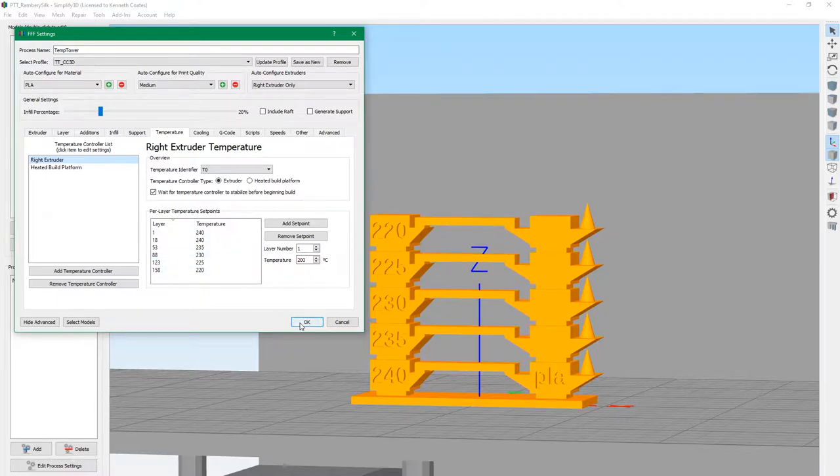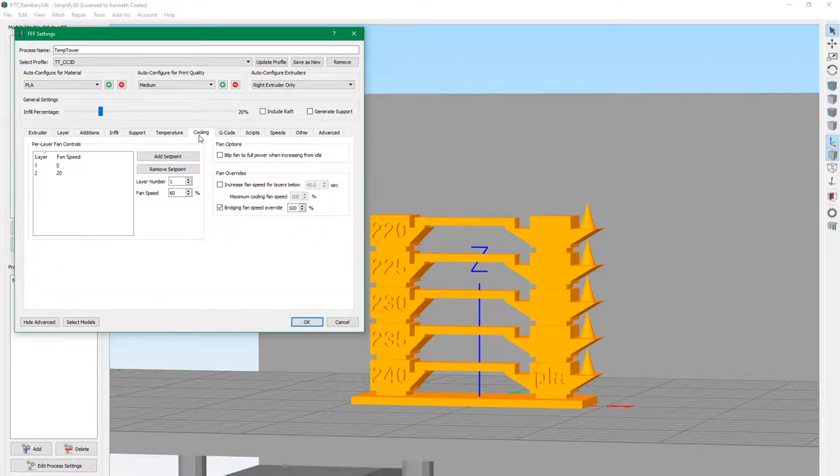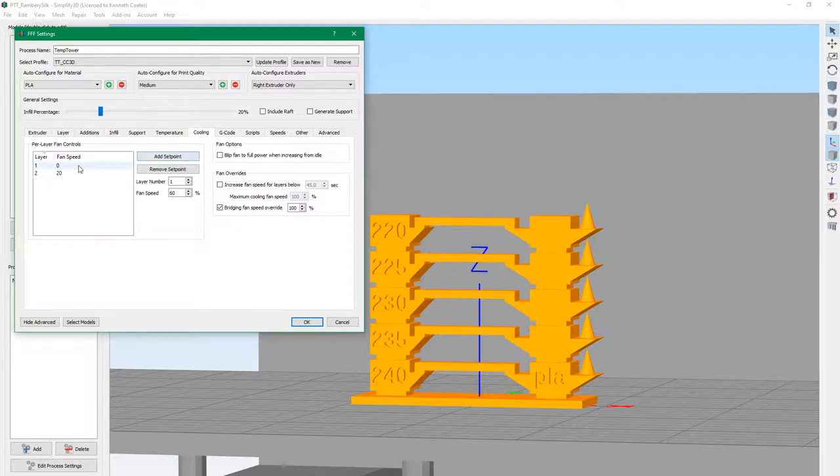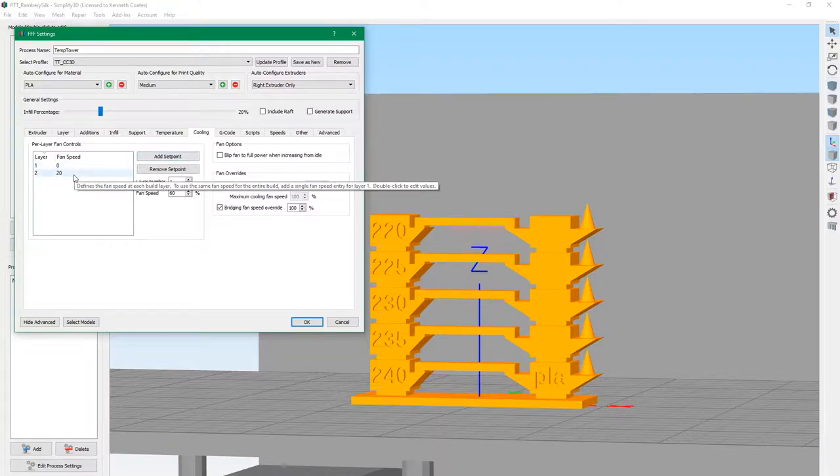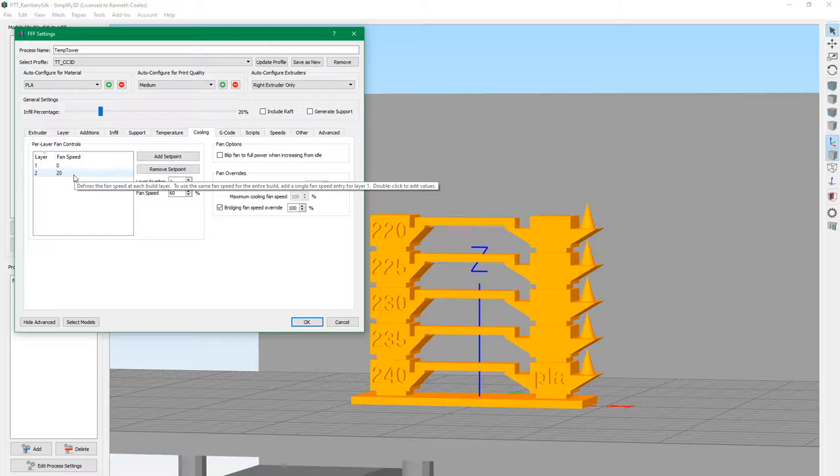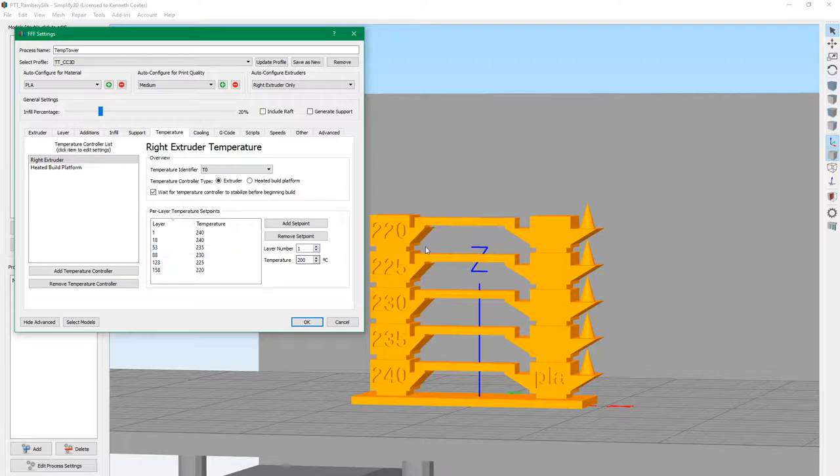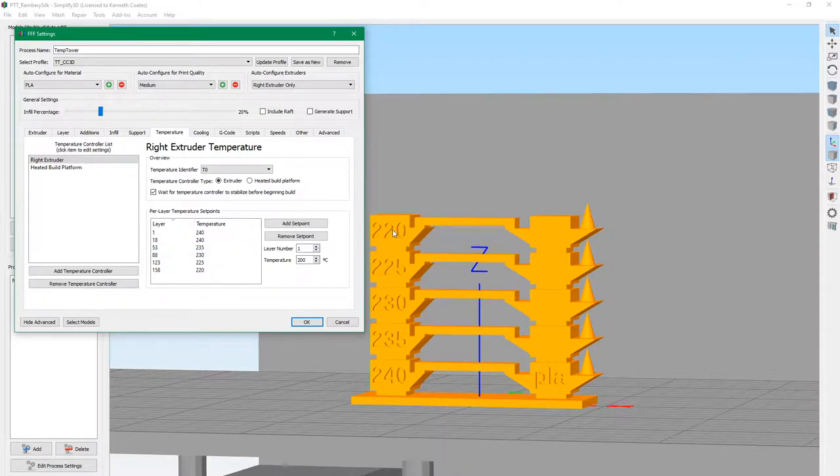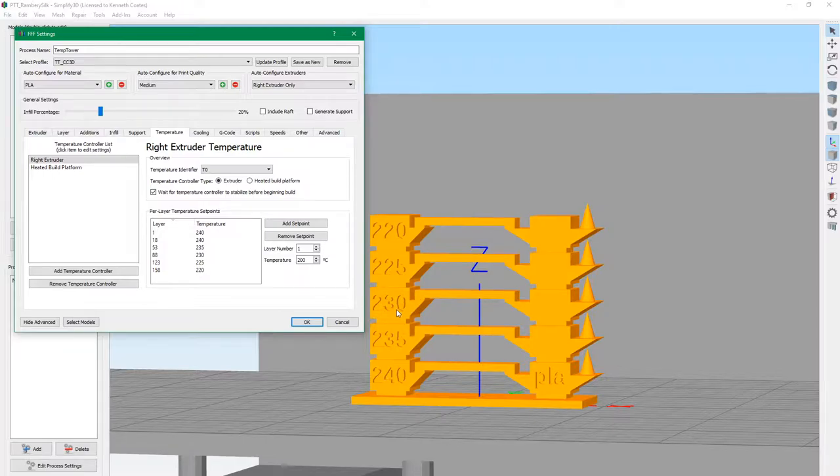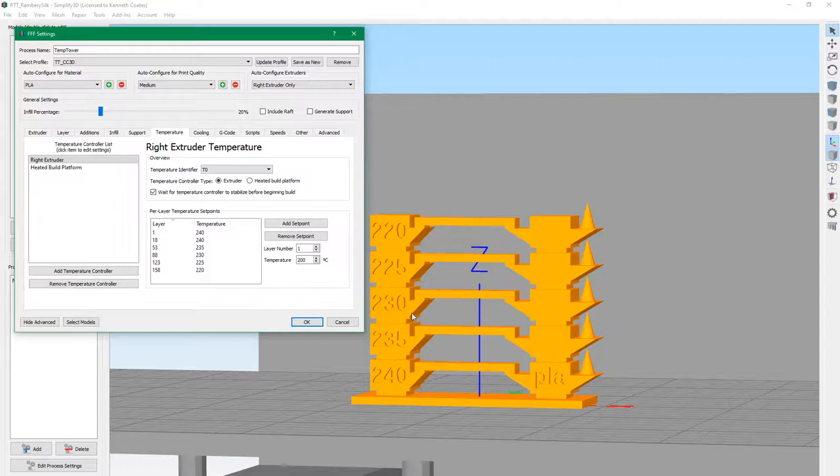In the cold garage we're only using 20% fan speed. Last summer we were using 100% fan speed, which I think is pretty typical for PLA, but it's just too cold. If you blow too much cold air on it, it just won't do any bridging. On the temperatures, normally in the summer we're printing at 220 a lot with our PLA.